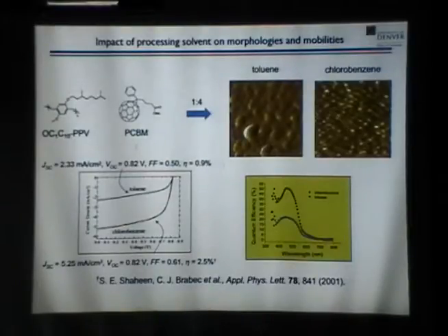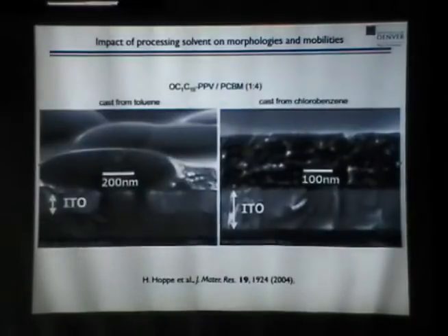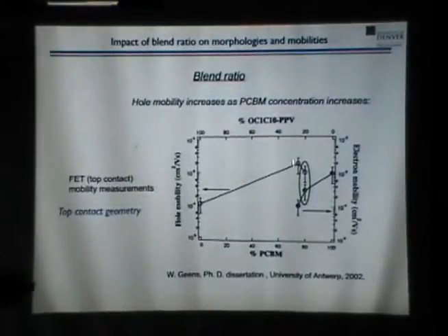That's probably a bad thing. If the fullerene and polymer are very close together, that helps in the recombination process. So the negative charge and the positive charge will come together very quickly. So in order to avoid that, you have to put in lots and lots of fullerene so that you get a phase or a domain that's pure fullerene. And then you can avoid this recombination process. So that's why we operate this at such a high amount of PCBM. Other materials don't have that intimate mixture and operate closer to 50%, where you would expect a balanced charge transport.